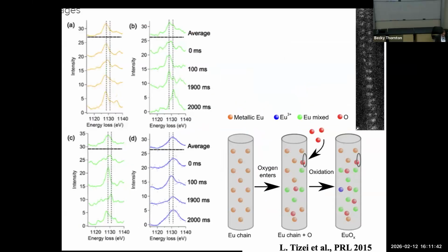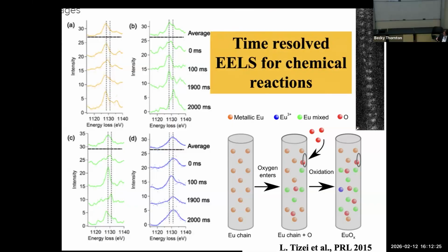If you have some sequential mapping, we could not completely track the reactions, but we see that some atoms do not react according to a simple chemical reaction scheme. I mean, they are sharing the electrons among several europium atoms. This is quite interesting, but we haven't gotten a clear answer from this kind of experiment. So this is how we interpret it. We are trying to track the single atom electronic state at millisecond time resolution or time intervals, so we could get some information on which state they have. Normally if you average, each atom shows two states mixed. This is the direction that we have to go for time-resolved spectroscopy.